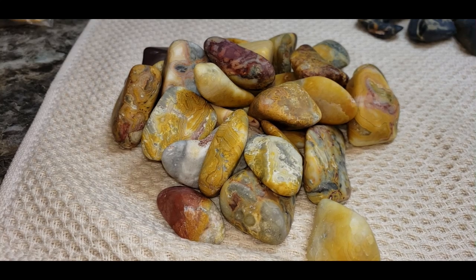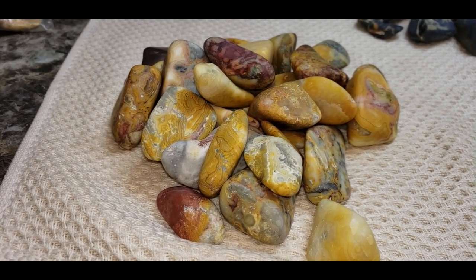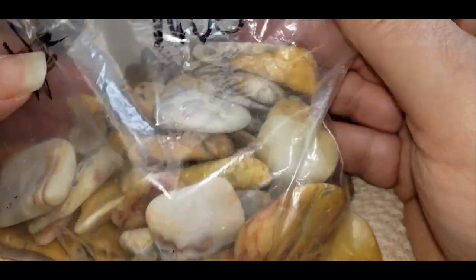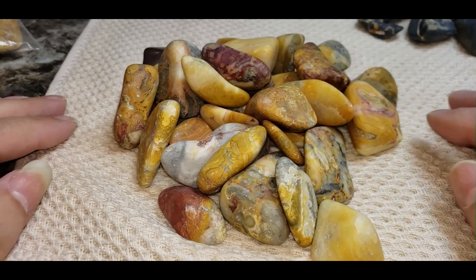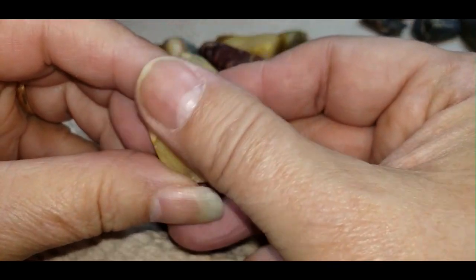It has been running 18 days in pre-stage 1, 46/70 heavy coarse silicon carbide grit, and then we put it in stage 1, 60/90 coarse silicon carbide grit, and it's been running in that stage for 6 weeks. Now we have split some pieces out and sent them to sit on the shelf waiting for medium, and let's see how many more pieces get to join that. This is what we were holding so far, and let's see if we can add anything to it. And this is dried because it dried out while we're filming here today, and we'll just wet it as we need to.